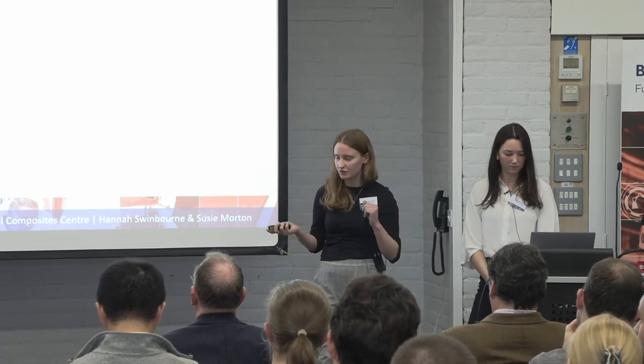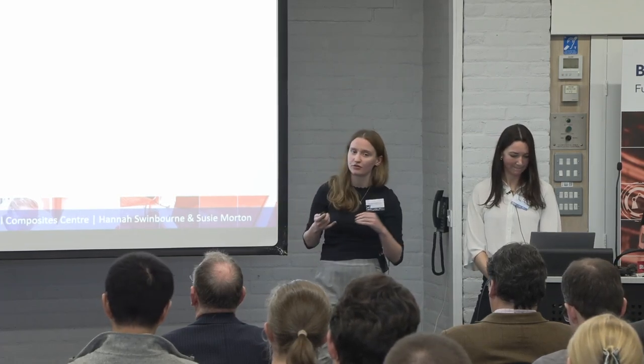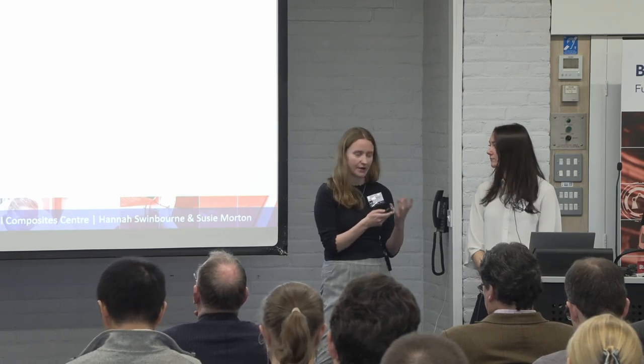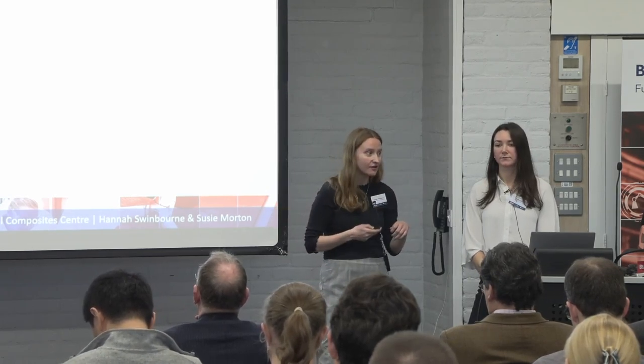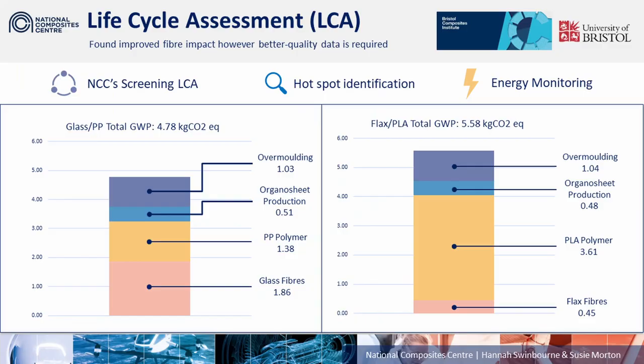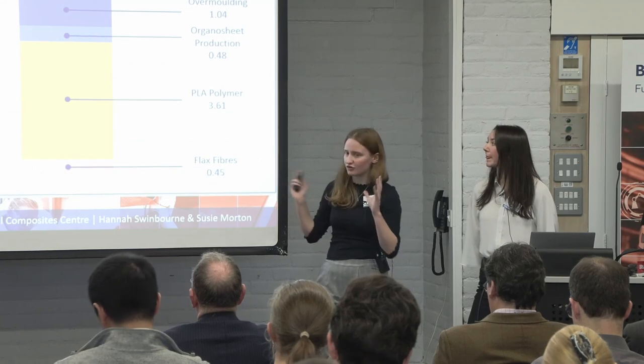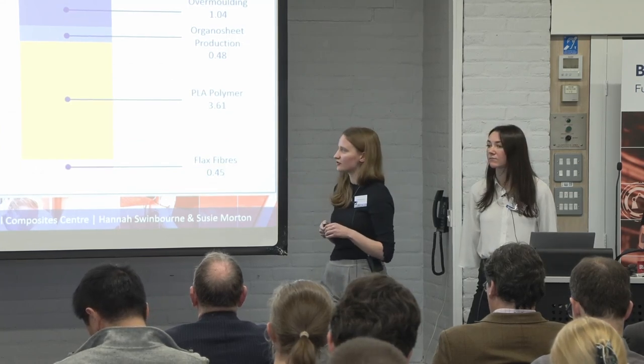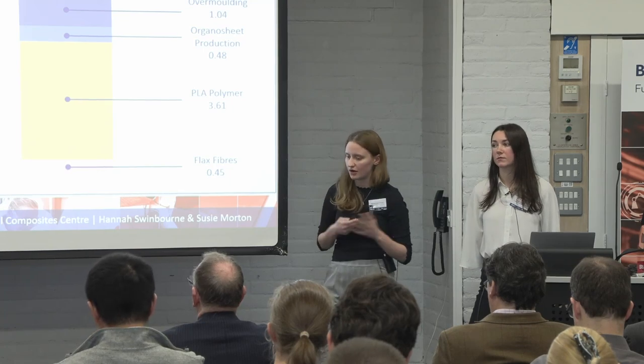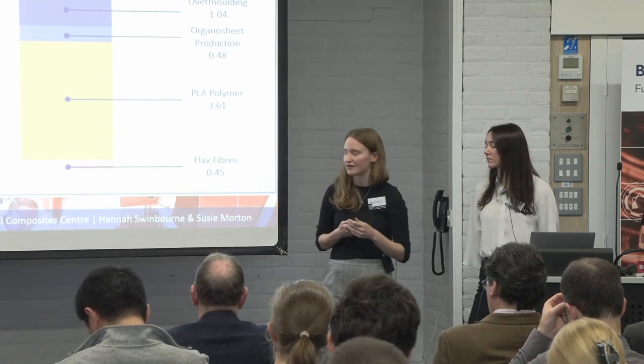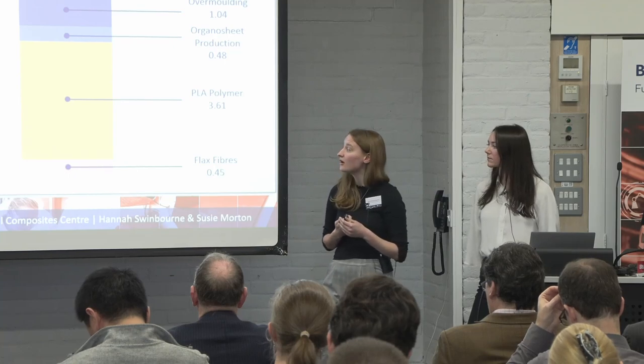We also used our energy monitoring capability to have a look at what the overmolder is contributing to the overall part impact. And interestingly, from these results, the thing you can probably see straight away is that the flax PLA came out with a higher GWP, global warming potential, impact. But this is actually entirely due to the PLA. And I just want to highlight, this isn't us saying that PLA is the devil, but just saying that maybe we need to focus on optimizing the production of PLA to make it more viable, as it is compostable.